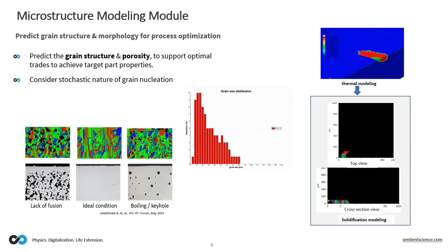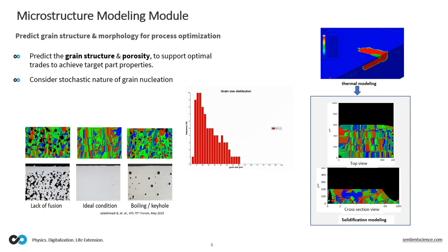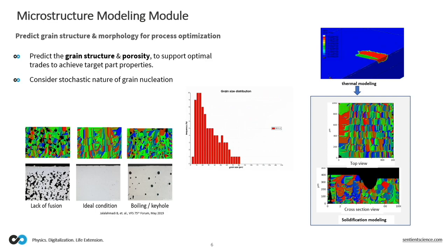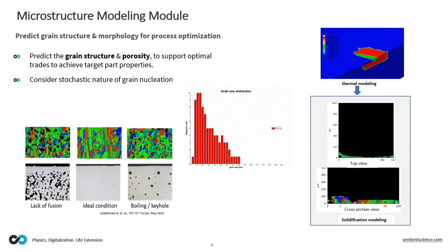Again, we are predicting the microstructure in 3D, and then of course we are making 2D slices, as you can see here in the movies, along the build direction and perpendicular to that one. Also, what you can see on the left-hand side, in our microstructure generator, we are also able to predict the porosity in the microstructure, for both reasons: not enough energy or too much energy. Basically, porosity that happens because of lack of fusion, or porosity when you're applying too much energy because of boiling and the keyhole effect.